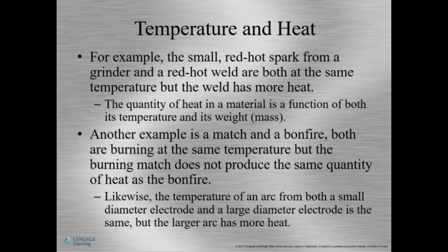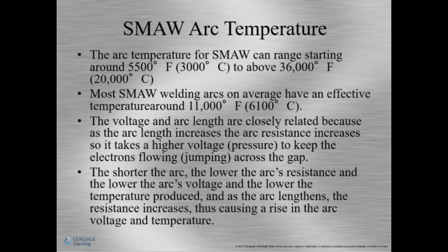Why? Well, the quantity of the heat in a material is a function of both its temperature and its mass. Another example would be a match and a bonfire. Both are burning at the same temperature, but the burning match does not produce the same quantity of heat like a bonfire. Okay, so the temperature of the arc from both a small diameter electrode and a large diameter electrode is the same, but the larger arc has more heat. So the bigger it is, the more it is. Okay, the arc temperature for SMAW can range around 5,500 degrees Fahrenheit to above 36,000 degrees Fahrenheit. Most SMAW welding arcs on average have an effective temperature around 11,000 degrees.